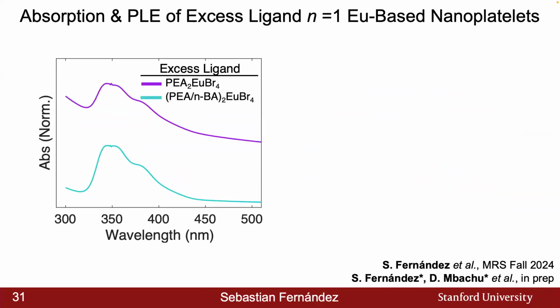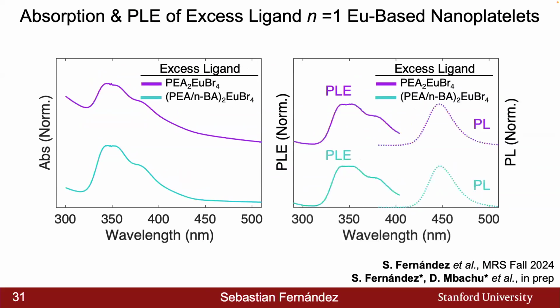But what if we look at the solution state for the optimized, the true N=1 nanoplatelets across various ligands as shown here? We can see that the absorption is still quite the same. We have the peak at around 350 nanometers, good adherence with the photoluminescence excitation and the PL. And this time we're able to achieve PLQYs as high as around 11.6%.